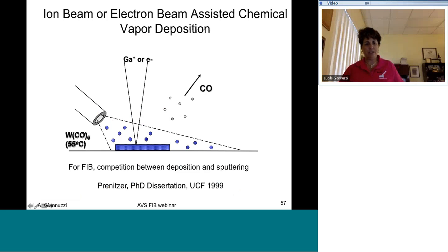For deposition, the idea is to insert the gas needle, generally set 50 to 100 microns from the sample surface. You heat up the gas to sublime the material, and this gas will go on for several hundred microns, if not longer. Wherever you raster the beam, whether it's gallium or xenon or even your electron beam, you're going to crack the gas, resulting in a deposit, and whatever doesn't get decomposed will be removed via the vacuum chamber.